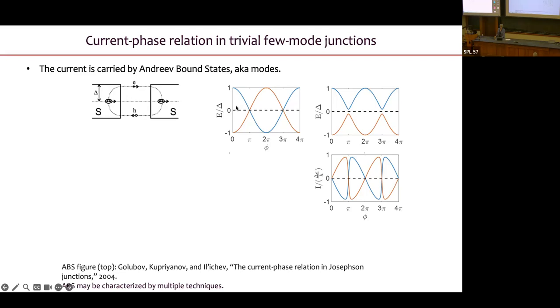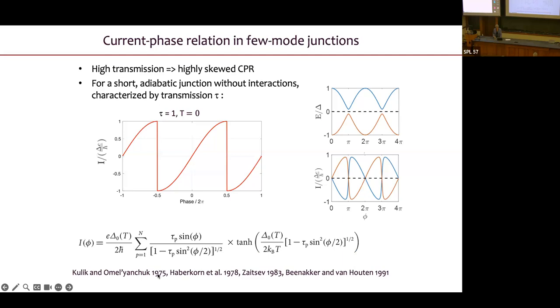There's an electron-like state and a hole-like state, and they cross, and then there's an avoided level crossing, and the current is the derivative of the energy with respect to phase. So the current of the two states looks like the red line and like the blue line. Okay, so that is the current phase relation. And then here's a more detailed expression of what the current phase relation looks like from a series of papers in the 70s, 80s, and 90s.